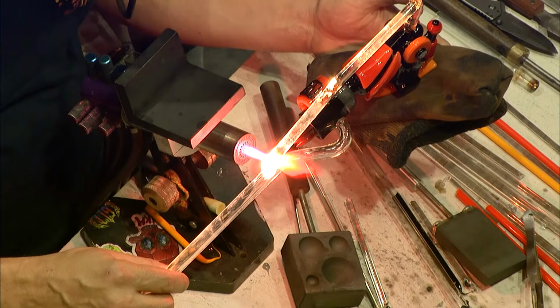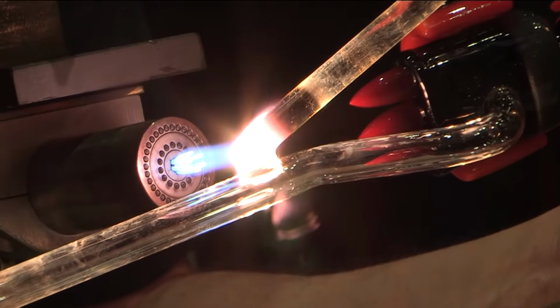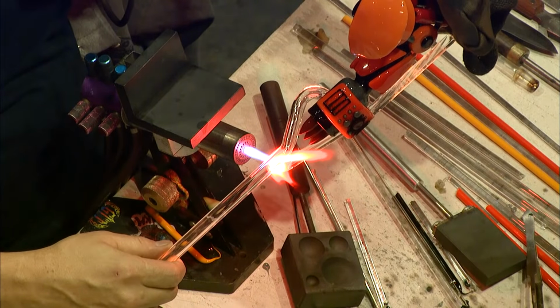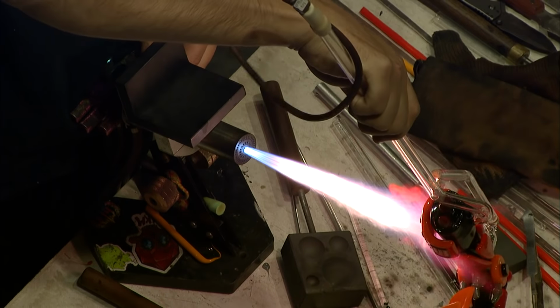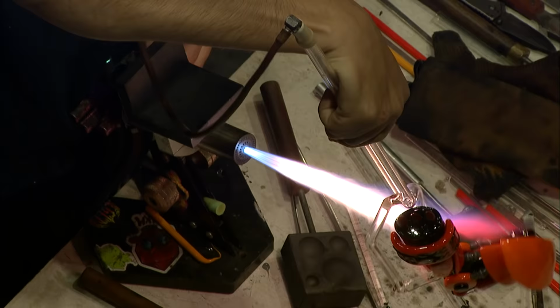How were the colored sheet sections made? Well, to make the sheets, they have done a combination of things. At times, they will take hollow tubes of the colored glass, open on both ends, heat the thing up so it's really ripping hot, and press them. They have some flat graphite mashers around here, so really just getting the glass incredibly hot, pressing down.